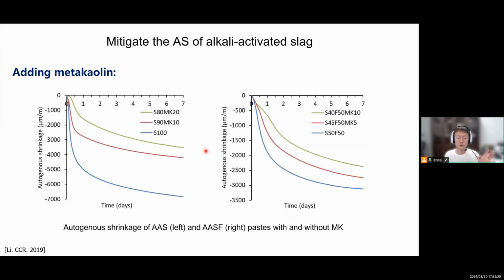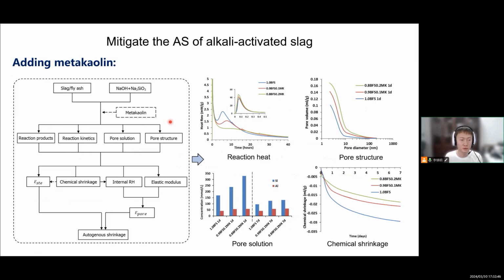So that idea didn't materialize, but the shrinkage is still reduced a lot, especially in the very early age. You can see from the blue to the green is reduced by more than half in the very early age. But the reason is not what I thought, the internal curing. No, it is because of something else. So through a lot of characterization methods, we clarified the mechanism. Actually, it is because the addition of metakaolin provides a lot of additional silicate and alumina. So it influenced the reaction products, reaction rate, pore solution, and pore structure.